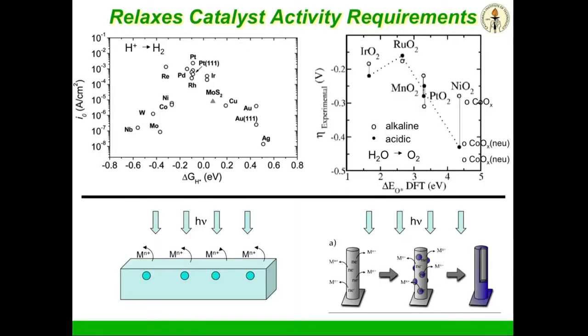And we've just shown this in a paper that we've just submitted, showing that we can in fact replace platinum with earth-abundant materials in this deeply integrated structure and maintain the same functionality with earth-abundant catalysts that are kinetically competent to match the solar photon flux, but only in these high aspect ratio structures. If you want to understand how important this would be, this is, on a log scale, the so-called catalytic breakthrough that comes out from our East Coast institution partners, cobalt oxide, and it's much lower in activity than other known systems, ruthenium oxide and iridium oxide. And the only way we can see to really use this is in this deeply integrated structure.